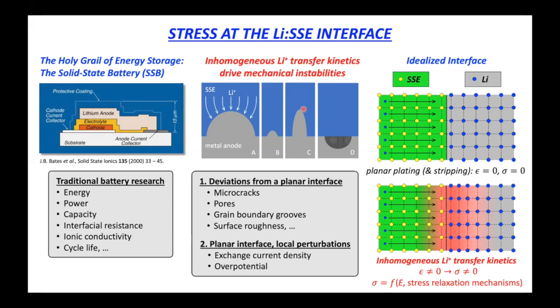And so the idea is that these three shapes physically represent some type of morphological defect in the surface of our separator. Right? And so those defects are going to be any sort of deviation from a planar interface: cracks, pores, grain boundary grooves, surface roughness. There's lots of possibilities there. And so these defects are presumably going to be filled with lithium. That's going to come from previous plating and stripping, or from an externally applied stack pressure, or some combination of all those things, right?